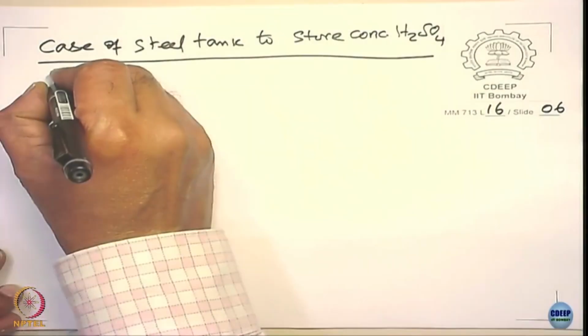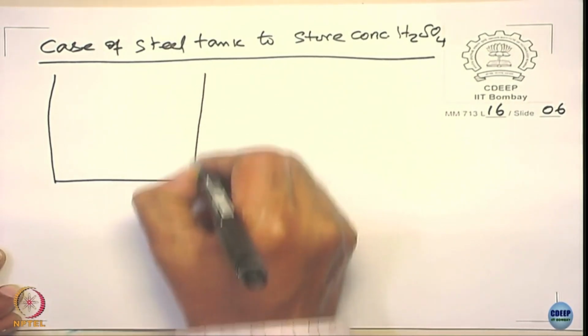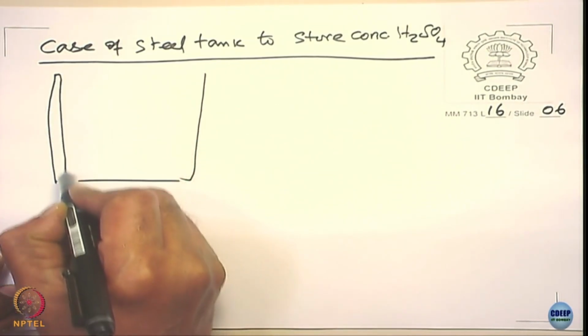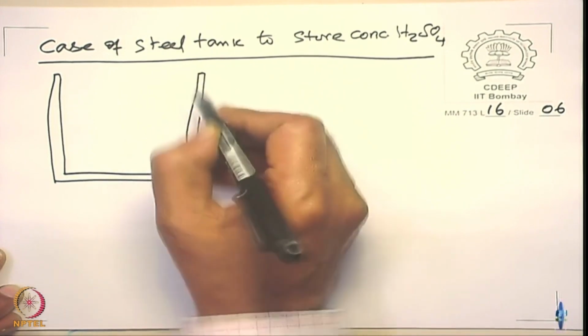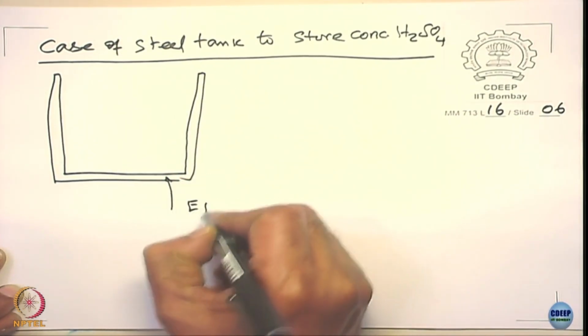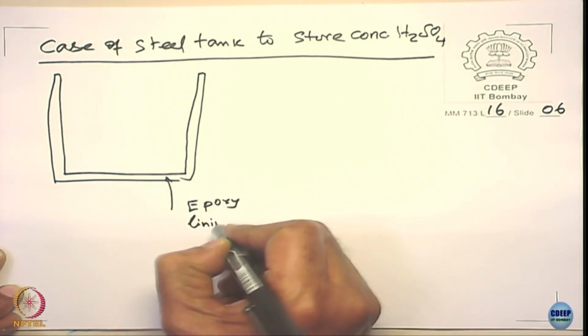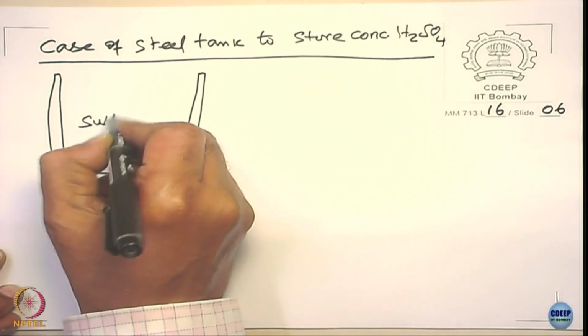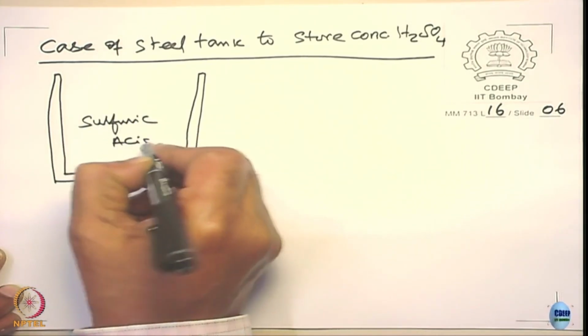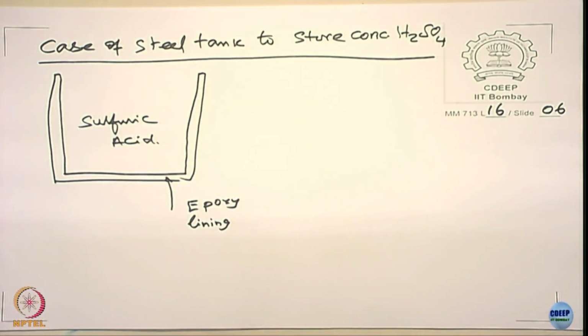Now, initially a steel tank was used, and they had this epoxy lining, and this is sulfuric acid. It is working well, okay. It gave us a few years of service, there is no problem. But what happens is there is always mechanical damage, people want to clean the tank. So, when you start cleaning the tank, the bottom of the tank more often suffered the corrosion, okay,